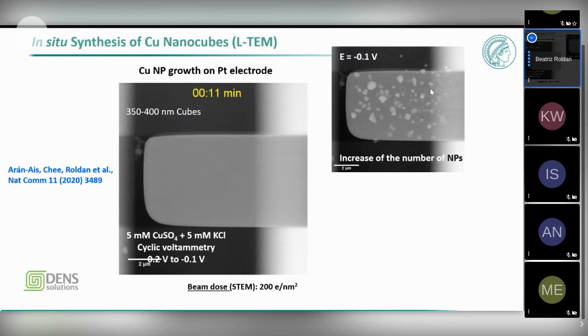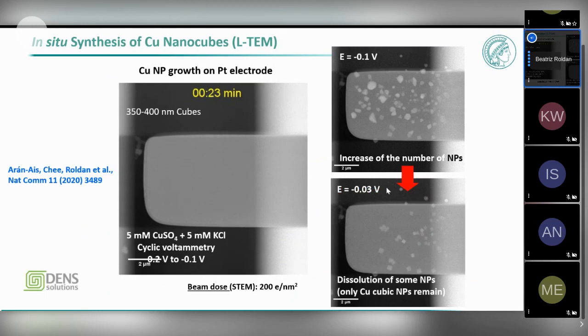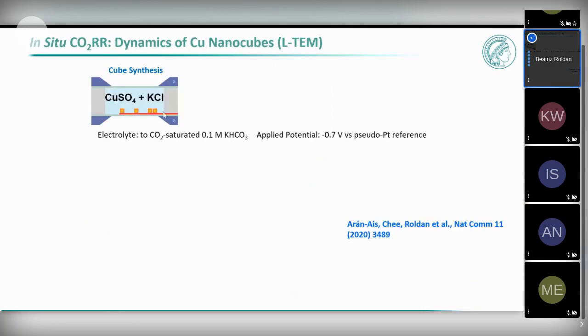All of this is copper, and if you go to the right potential with the right concentration of chlorine, you only get cubic structures. So now I have synthesized my catalyst in situ. I have size-controlled and shape-controlled nanoparticles, and now I'm going to go further and change the electrolyte. I don't want to grow anymore, so I remove this copper salt and I put in my normal potassium bicarbonate electrolyte that I use in all my talk today for doing CO2 electroreduction.